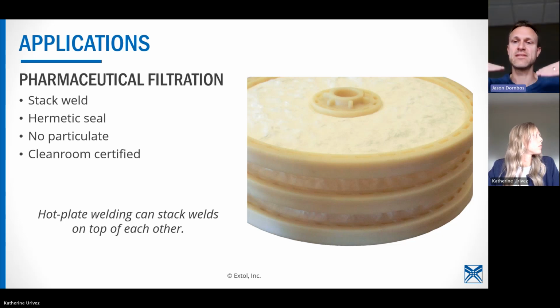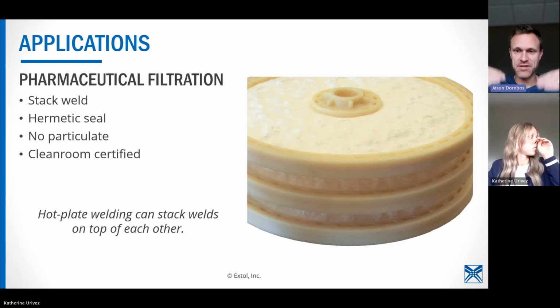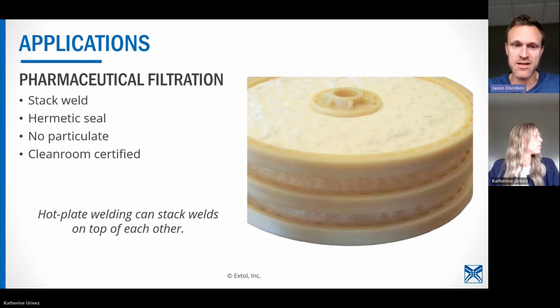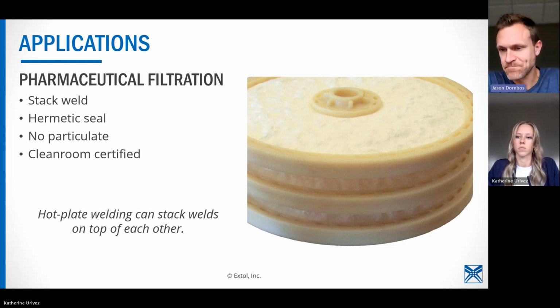If you have a consistent weld plane and you need to stack multiple layers on top of each other, that's something that hot plate welding can do, and particularly servo-driven hot plate welding. You need that welder to adjust its parameters between every single layer because the part is getting taller on one side while it's staying shorter on the other side. So in pharmaceutical filtration, we are able to do stack welding. Again, hermetic sealed, no particulate. It's clean room certified, so you're able to get good parts out of it, and you don't have to worry that you're going to have to clean the parts afterwards.